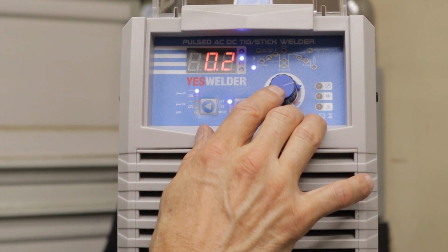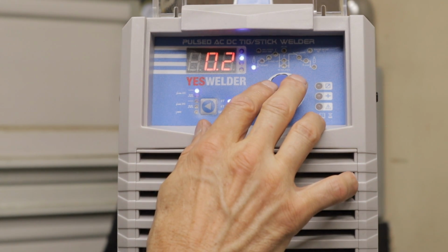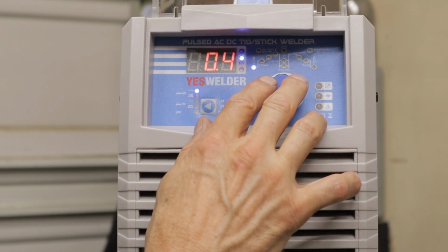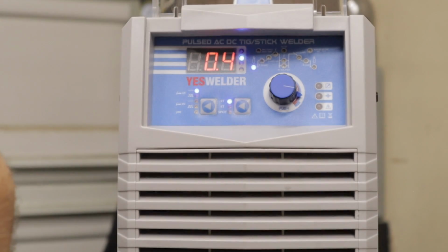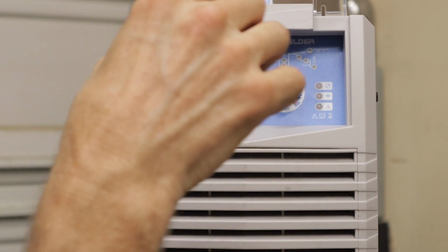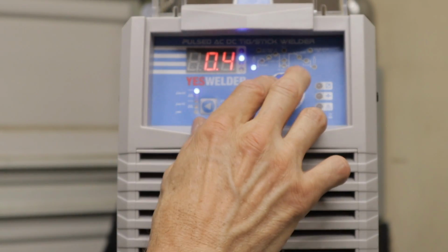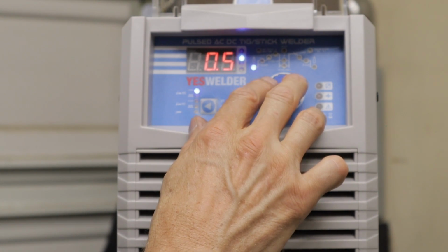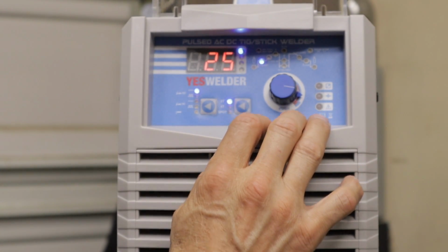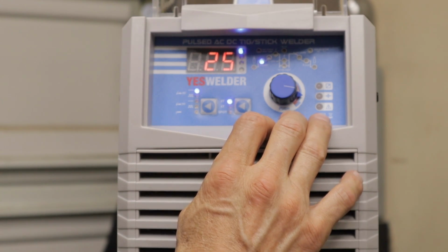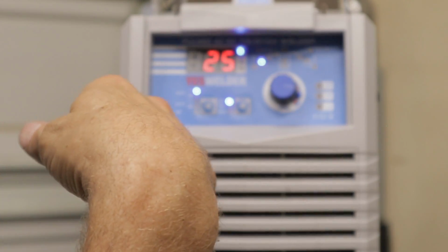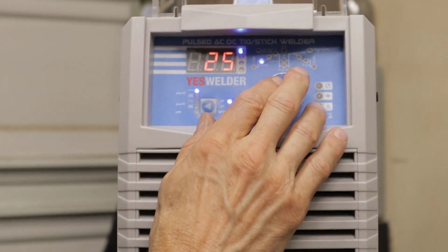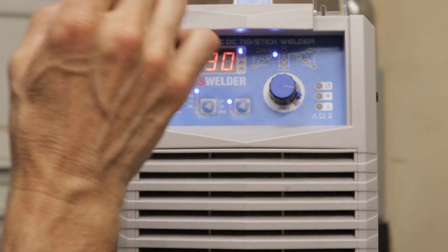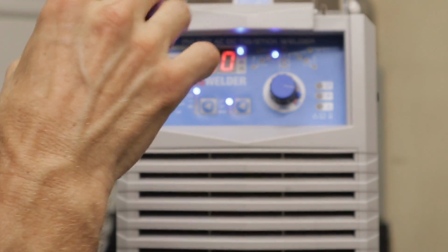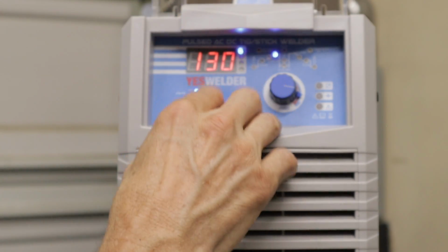Next we have our start gas. I have it start usually 0.2 to 0.4 of a second before the arc starts, before the high frequency starts. Next thing I do is your start amps. This one's set at 25 right now, just to get the arc started. I usually don't go down below that unless I'm welding really, really thin, because it gives you a better jump start on your high frequency start, just to have a little bit more amps. If you're obviously welding really thin sheet metal, you're going to bump that down.